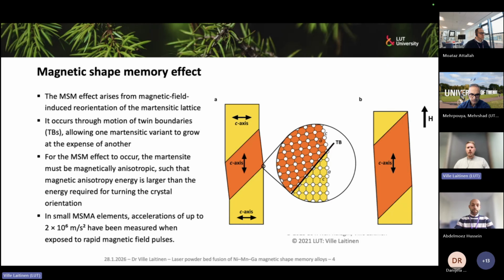In this figure, we have a 10-layered modulated martensite, which, if you consider the original cell of this L21 austenite, is actually a tetragonal cell. And this tetragonal cell has axes A, B, and C, where A and B are approximately equal to each other, and the C axis is shorter. But what is nice with this material is that we have these manganese atoms, placed by nickel and gallium at just the right distances from each other, so that we actually have a magnetic moment on those manganese atoms. And this material effectively becomes ferromagnetic, and this C-axis, the shortest crystallographic axis, is also the easy magnetization axis.